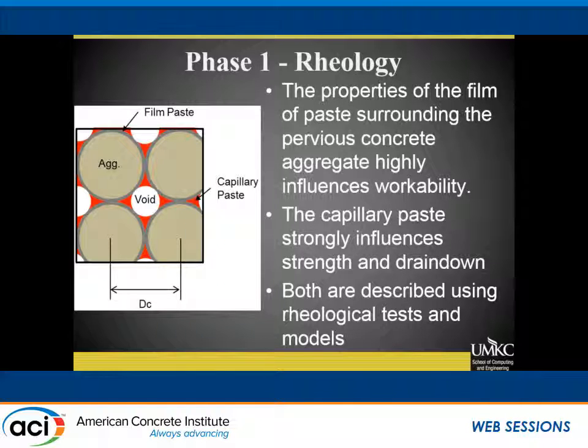And then you're going to have a little bit of extra paste that adds your capillary paste that helps stick those things together. And so the idea is, if you have too much capillary paste, then you've got regular concrete. If you don't have enough capillary paste, you don't have sufficient bonding between those particles to resist any forces, and you just have cement-coated aggregate that's out in the field. We definitely don't want that.